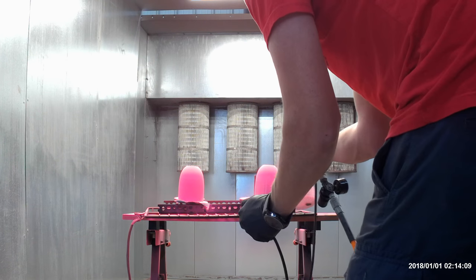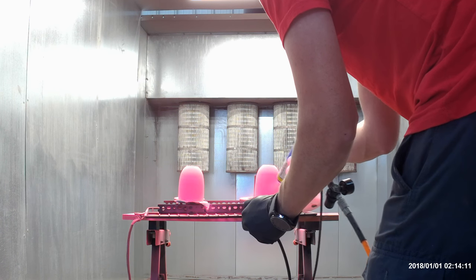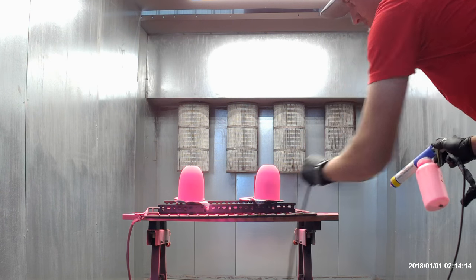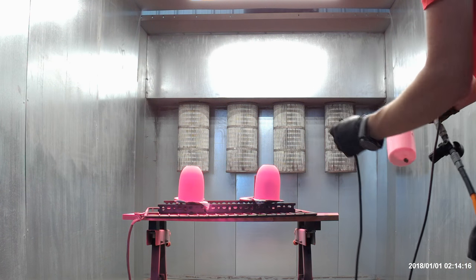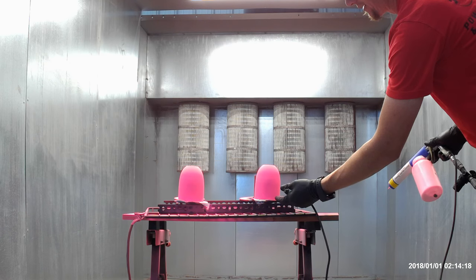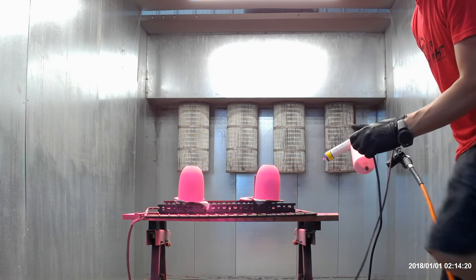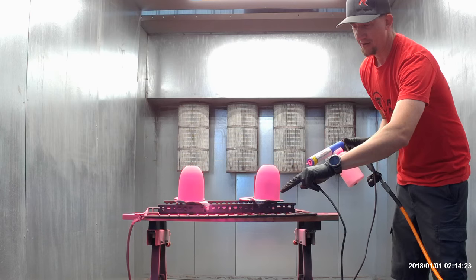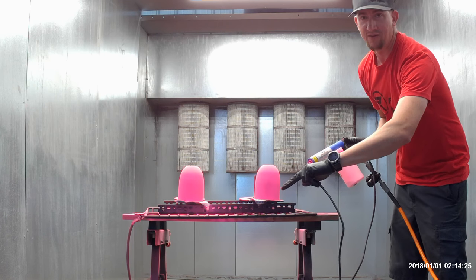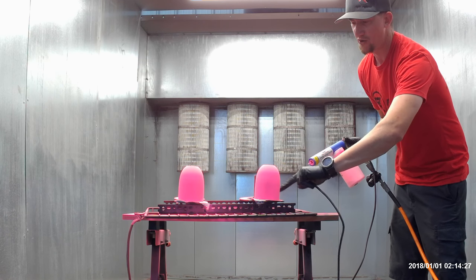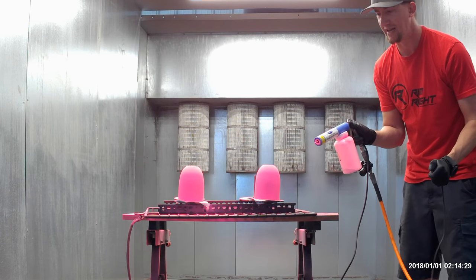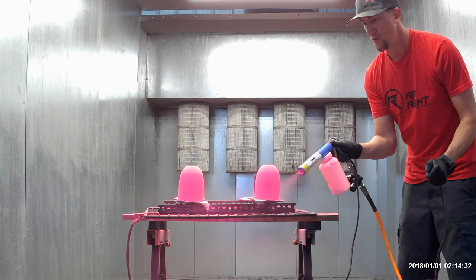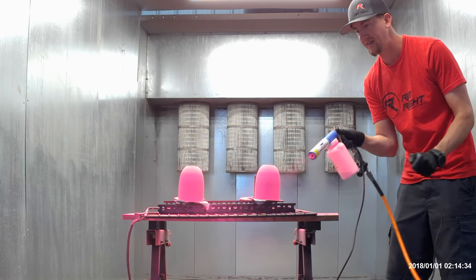As you can see on the bottoms here, it becomes really hard to get powder to stick. Basically it's a metal plate underneath. It creates a Faraday area, which is basically an overcharged area. When the particle goes in there, it's so charged—there's so much going on—it wants to bounce back out. So with any corners, anything like that, you'll struggle with it. With a little practice though, you'll start figuring out how to get those areas covered better and better.